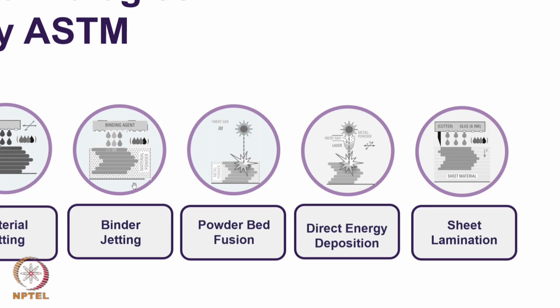So, some of you may be thinking, what are these supports? If the area that has to be supported is very simple, you can use some ceramic blocks, pre-formed ceramic blocks. You can just insert it in the debinded part, which is also called as the brown part, and then you can send it for sintering. Or while 3D printing itself, you can print the support, but not attached to the part, right.